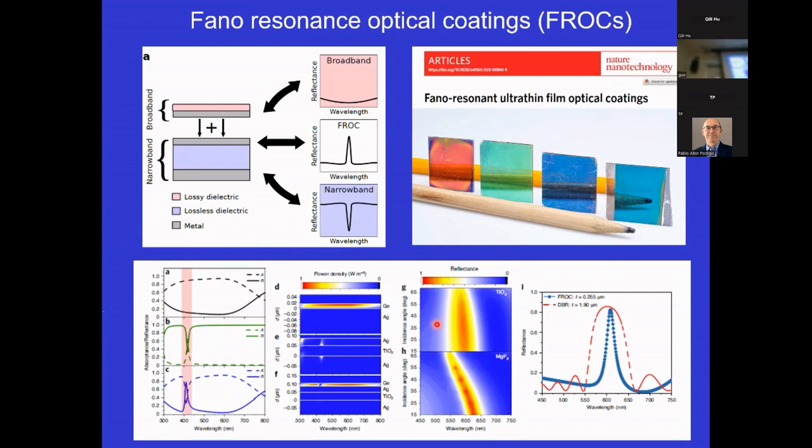Well, if we don't do this from the Institute of Optics, where should we do this? We know this old technology, optical coatings. The key is having the broadband absorber and narrowband absorber, integrated together. We can integrate with coating. So the top layer is a broadband coating. What will give you broadband is a lossy dielectric, typically germanium, put on top of a metal layer, silver, then you have a broadband absorber.